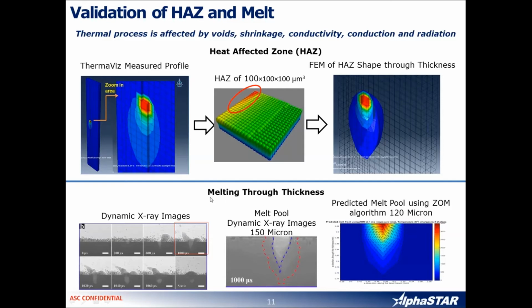On the bottom, we're going to look into the melting through the thickness. There is a dynamic X-ray image shown on the bottom left of the melting through the thickness, and one of the regions here is magnified, and you can see it shows the footprint of the dynamic of the melt pool, which shows about 150 microns. On the right-hand side, we do the prediction using ZOM algorithm, which also shows very close to the available X-ray test, about 120 microns. And this also takes seconds to run the analysis.